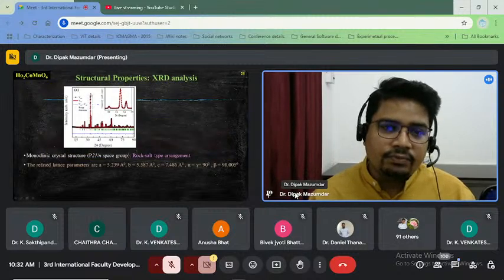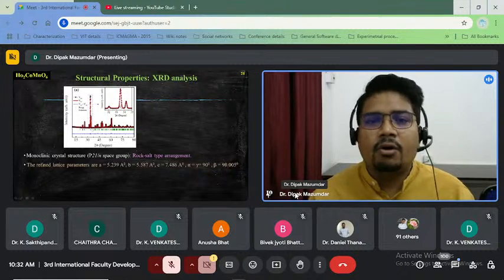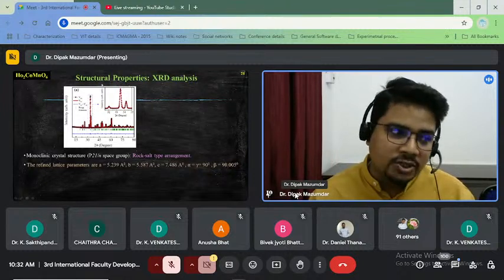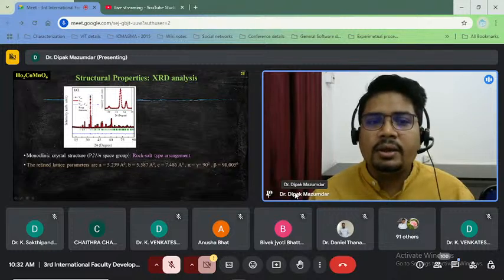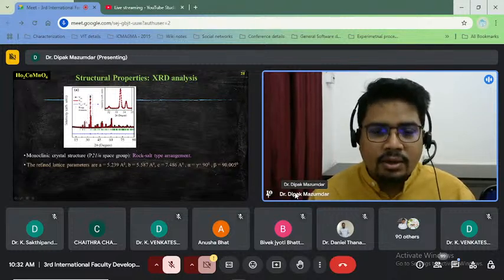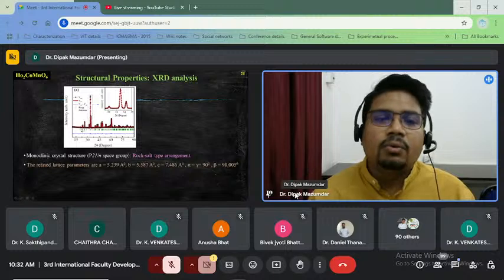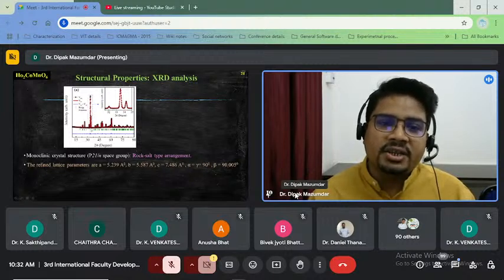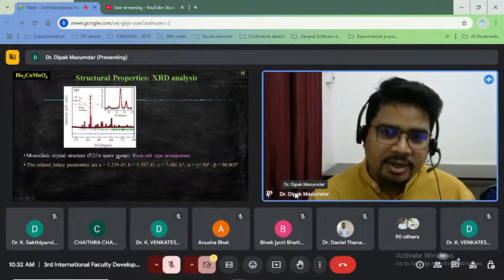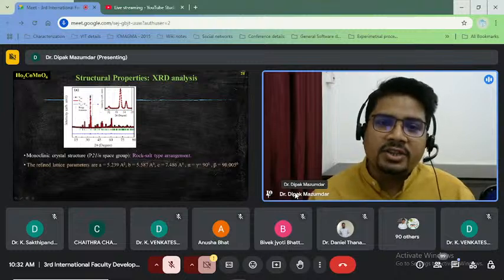So this is a full Rietveld analysis of the obtained XRD pattern at room temperature, and we can see that all the peaks, the black one, experimental data, were well fitted with monoclinic crystal structure, P21 space group, and you can see the goodness of the fit.